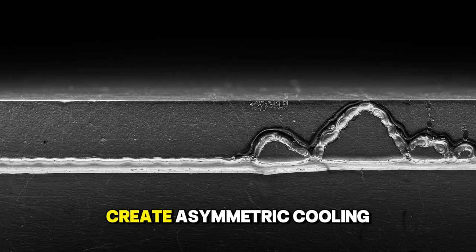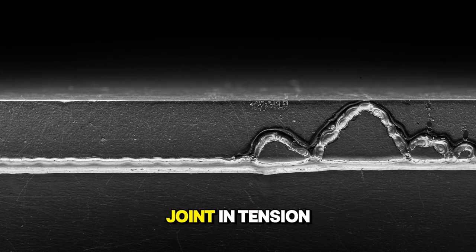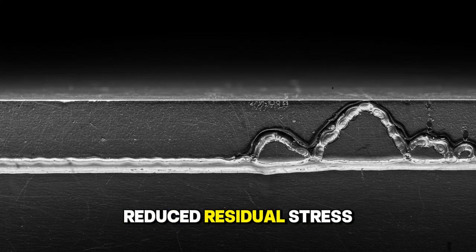Standard butt welds create asymmetric cooling patterns that leave the joint in tension on one side, which makes it more susceptible to brittle failure under impact. The double V joint's symmetric heating and cooling reduced residual stress significantly. The weld was in a more balanced state, more ductile, better able to absorb energy rather than fracture.